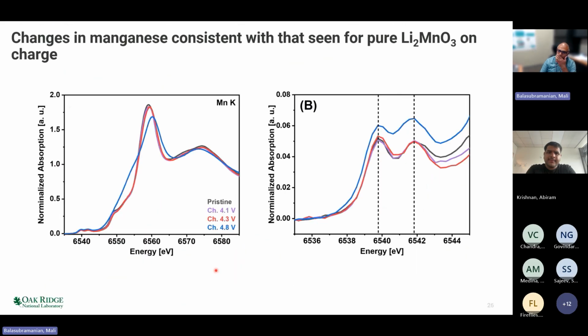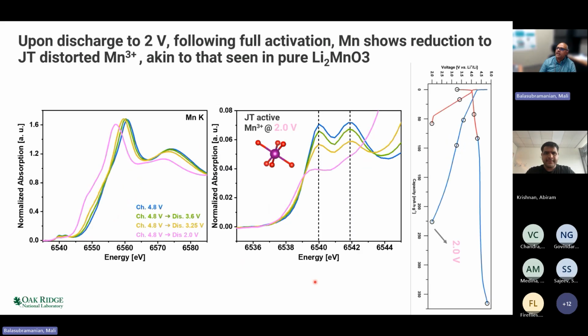Now, because of the short amount of time that is there, I'm just going to show that the manganese XANES is consistent with Li2MnO3, but when you go to 2 volts, there is a huge reduction of manganese. This is similar to what happens in pure Li2MnO3 systems. That is, manganese reduces on discharge. This is unlike what is usually seen in the nickel and manganese based systems, where oxygen redox is reversible. So we don't see much evidence for reversible oxygen redox, but we see a reduction of manganese similar to pure Li2MnO3 systems.